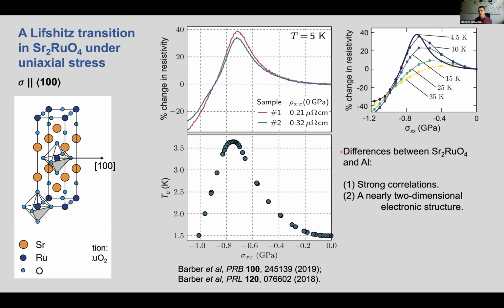So the differences between strontium ruthenate and aluminum, one of them is that strontium ruthenate is simply a much more strongly correlated metal, but the other one is that it has a nearly two-dimensional electronic structure. And so with the three-dimensional metals, at the Lifshitz transition itself, you have a divergent local density of states, but the total density of states does not diverge. When you have a Lifshitz transition of a two-dimensional metal, you do have an actual divergence in the total density of states. So a much stronger anomaly in the density of states and much stronger effects.